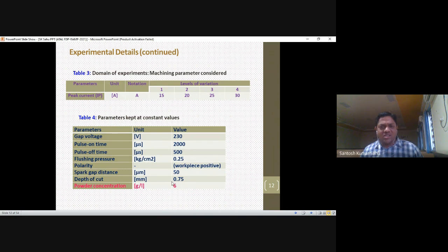Whatever material is removed during the on time should be removed in the off time. Before the next on time, the machining area should be cleaned out with the help of proper flushing. If you do not provide proper flushing during the off time, then the removed material will not be cleaned out from the machining area, and there is a chance of re-welding in the machining area. Then there will be an effect: the white layer thickness, which is called the recast layer.